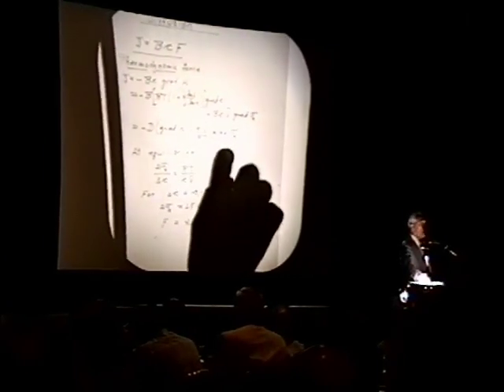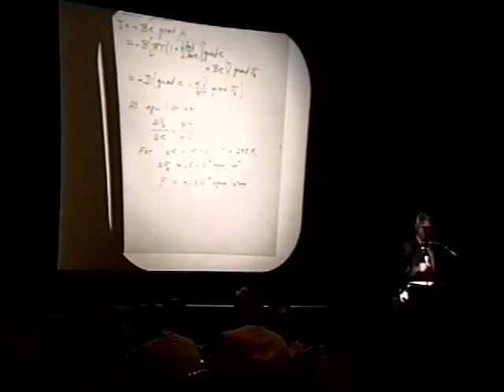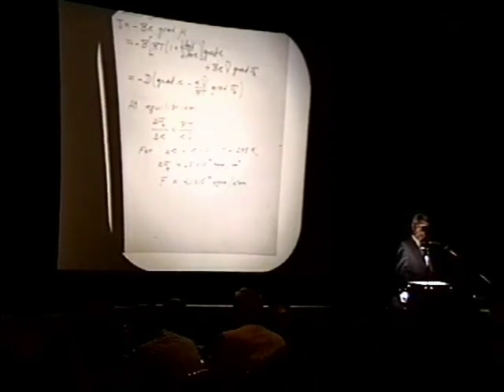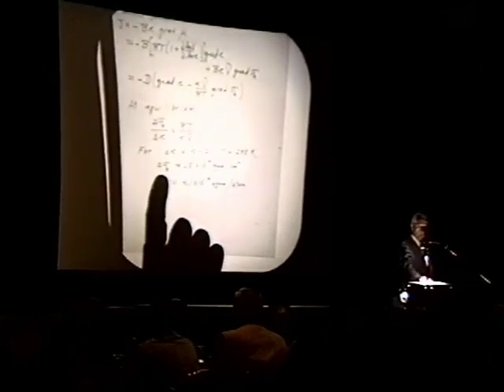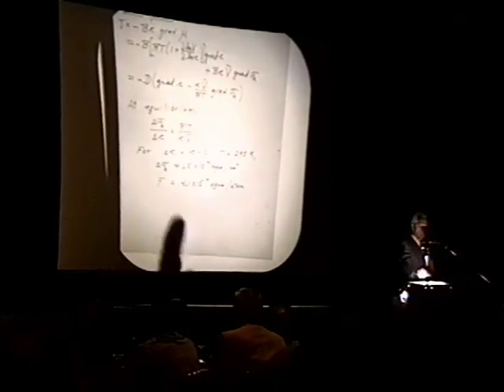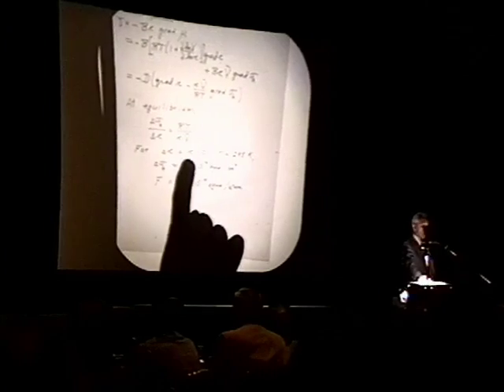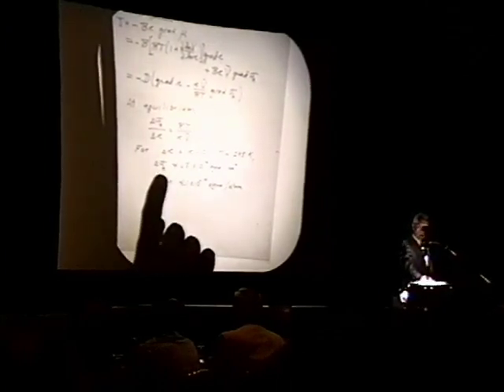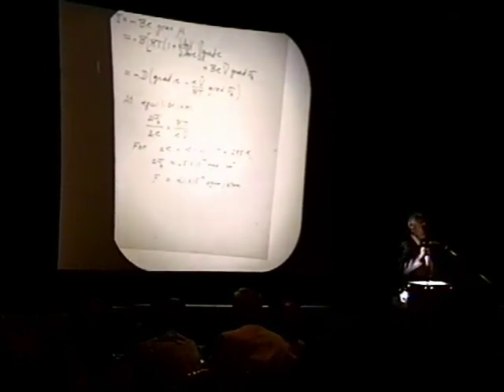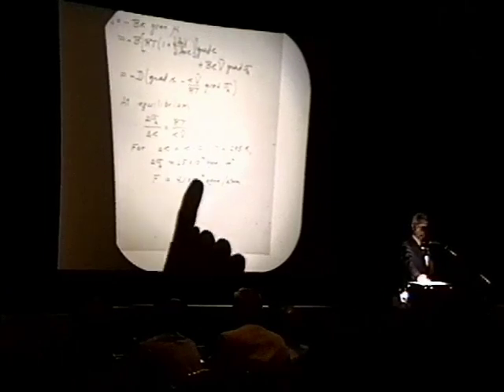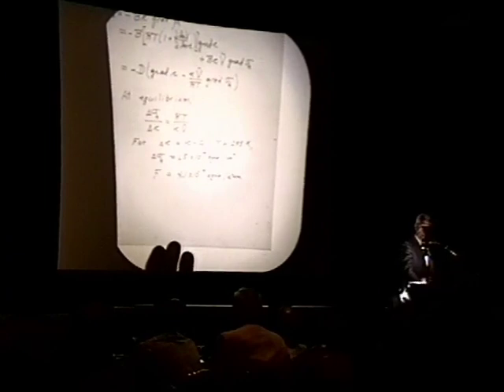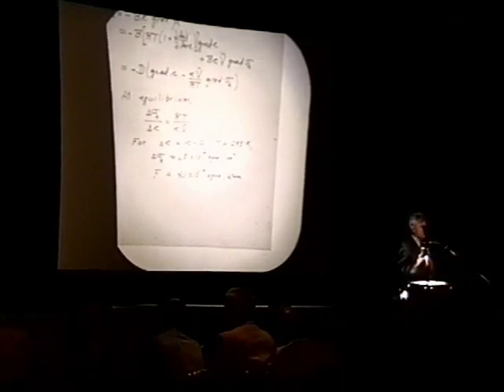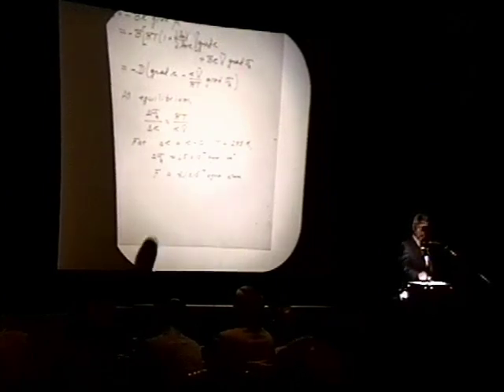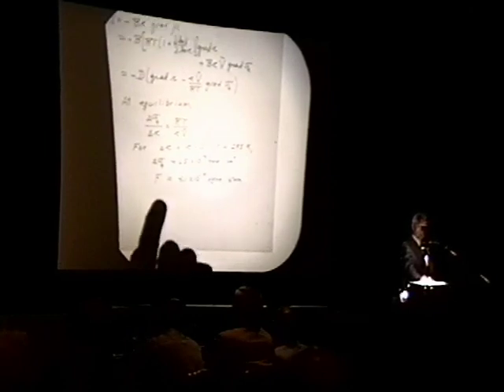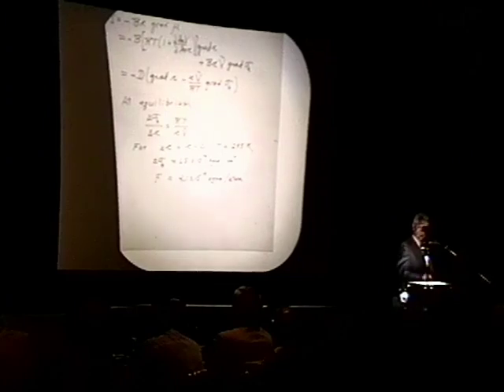Now actually, this is not a minor ingredient in the process, because at equilibrium, say at a temperature of 295 Kelvin, you find that there are two points between which there is a delta C, a concentration difference. That delta C can be counterbalanced by a difference in the hydrostatic component of stress of this magnitude, 1.5 times 10 to the 10th dyne per square centimeter, and no diffusion will occur. So it's a major contribution. The force that is motivating the flux under a stress gradient can be expressed this way for these conditions.